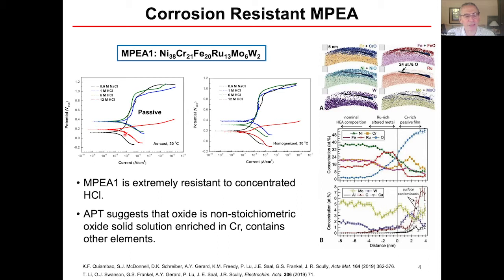And you can see that these are passive, spontaneously passive, and even giving pretty low corrosion rates in this 12 molar HCl, though kind of active dissolution in that environment. I'll tell you that the as-cast, again, I'm not focusing on this alloy, the as-cast is indeed a single solution FCC, although it has dendrites and coring, so there are compositional gradients. Nonetheless, this alloy is extraordinarily corrosion resistant.